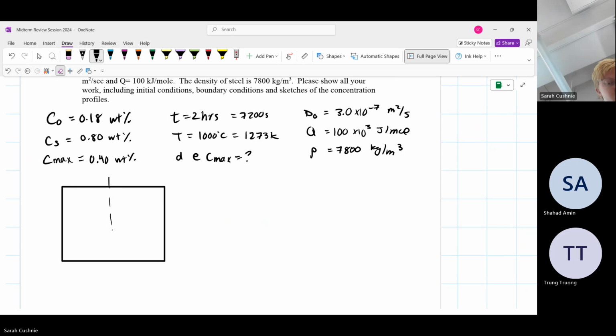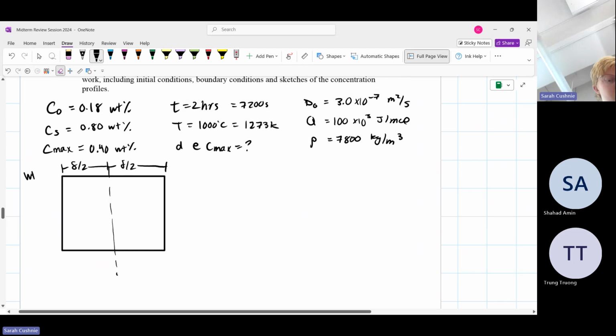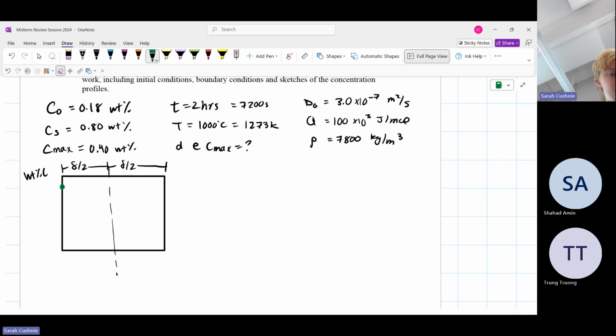So we have some halfway mark. I'm going to call this right here the thickness divided by 2. And this is the thickness divided by 2, where delta is the entire thickness. And I'm going to write the weight percent carbon on the edges. Initially, we're going to have fixed on the edge 0.8 and 0.8, down to 0.18, because remember, that was the initial condition. 0.18. I'm also going to call this CS and C naught.